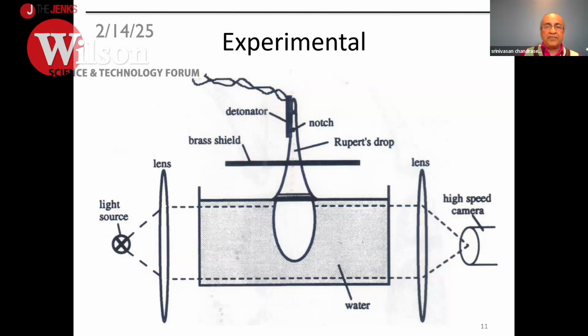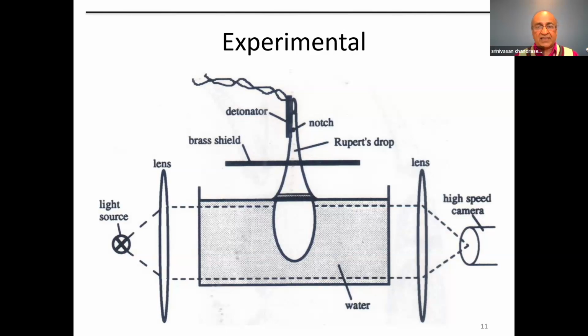So here you see the experimental arrangement. So you have a drop. Some of the experiments will be done in water, and some will be done in glycerine to match the refractive index so that you can see through the drop better. And then some are just done in air. So you have a drop suspended in a chamber. There is a light source at the left, which is a xenon flash tube that lights up for about 150 milliseconds. The right-hand side is the high-speed camera. The optics, the focusing, is shown here. And then on the tail of the drop, we make a little notch, and then we attach the detonator, and then we ignite the detonator.